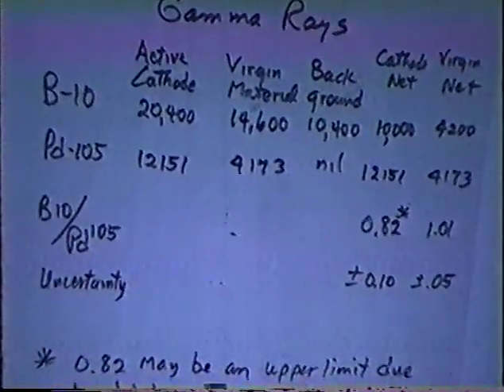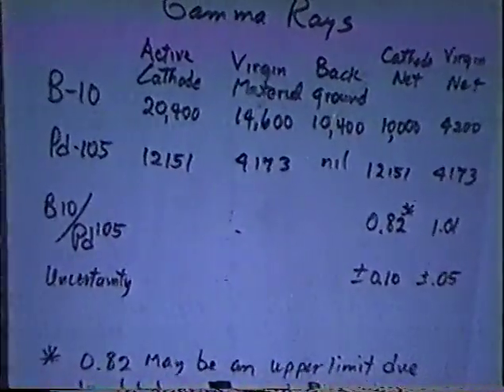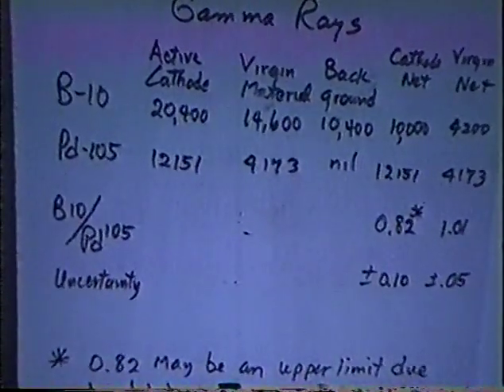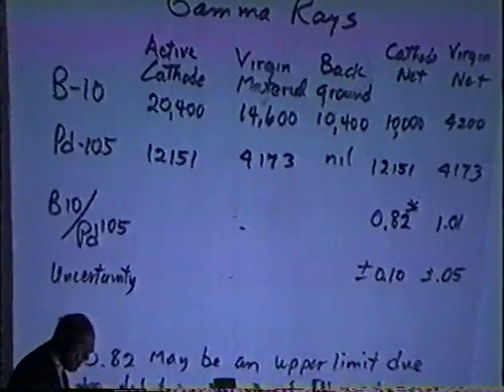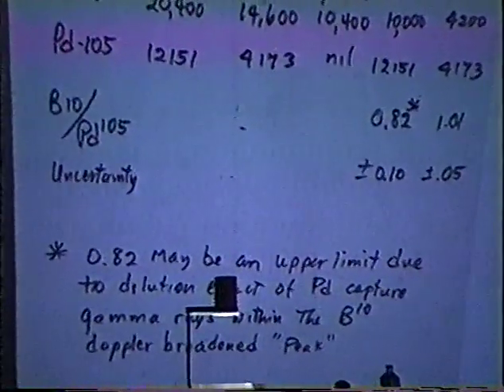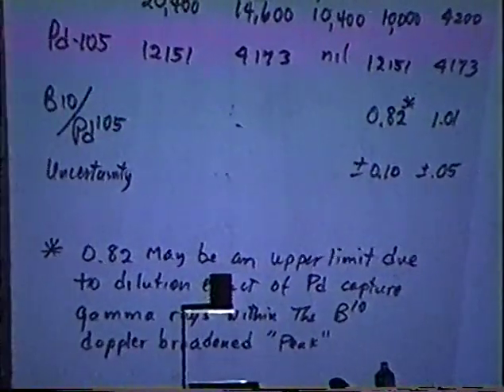And you can see these are not as accurate as you would like because of the strange shape of that overall sort of modified square peak of boron 10. In the case of palladium 105, I have some very good statistics here. Not quite that good, but at least much better. And with a nil background, the nets are here.